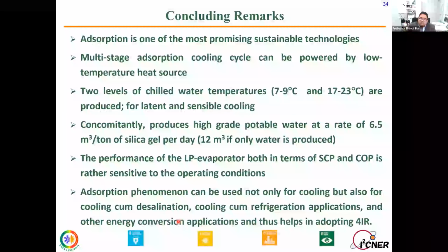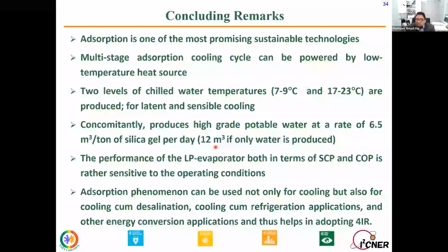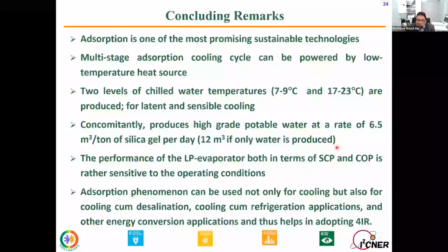And with this note, I want to conclude my talk. I can say that adsorption is one of the most promising and sustainable technologies, and a multi-stage adsorption cooling cycle can be powered by a low temperature heat source. Two levels of chilled water temperature, from 7 to 9 degrees centigrade and 17 to 23 degrees centigrade, are produced for latent and sensible cooling. Concomitantly, it produces high-grade potable water of 6.5 meter cube of water per ton of silica gel per day, or you can improve it to 12 meter cube of water if only water is produced in the same cycle.